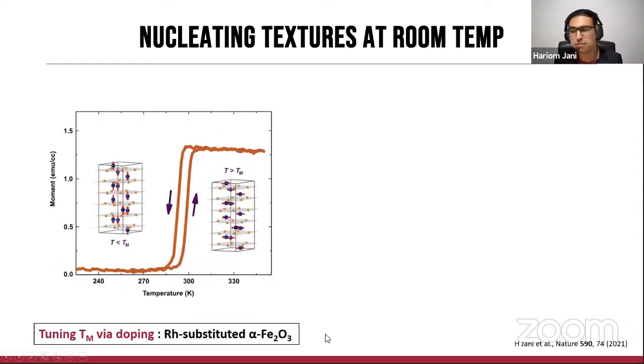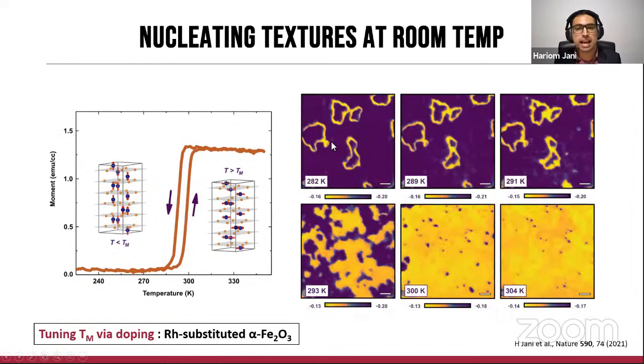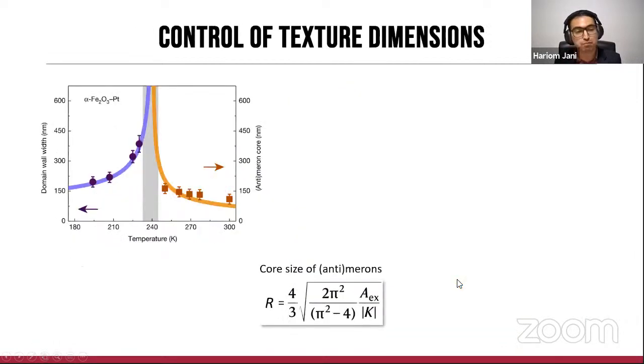This is actually quite straightforward and very well known in the Fe2O3 antiferromagnetic community, that by doing doping, you can actually shift the Morin transition either down or up. In the case of rhodium substitution, we delicately tune the effective single ion and magnetic dipolar anisotropy such that the transition now sits at room temperature, and the same phenomenology that we've seen below actually repeats here as well. So it is very possible to actually use this functionally by curating the transition as desired.